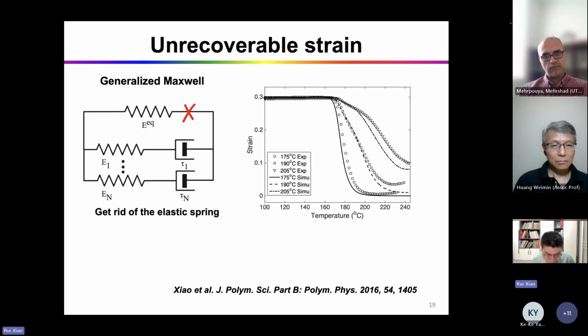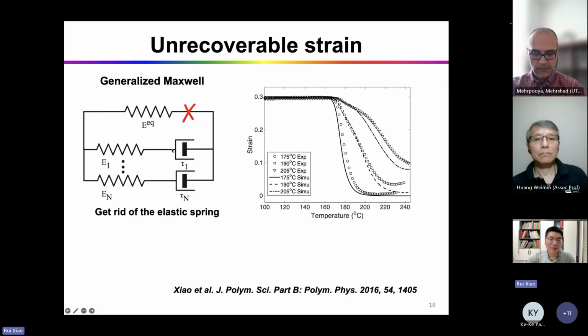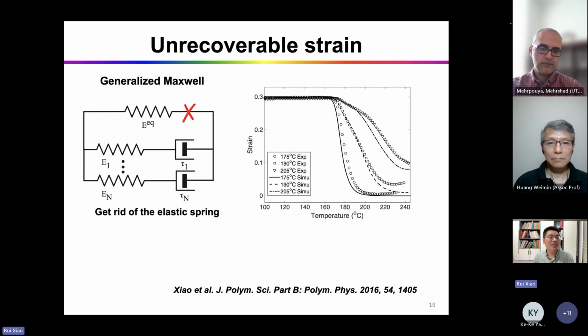But we would like to ask, if you do not have a permanent shape, why still have a very high recovery ratio if you program it at low temperatures? The model can tell you something like this: if you program at low temperatures, these relaxation processes have a very long relaxation time. They act the similar role as the cross-link networks, so these networks, like well-defined cross-link networks, can recover and fix the permanent shape.